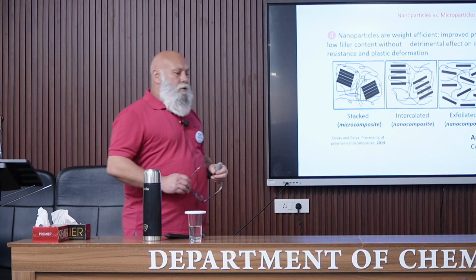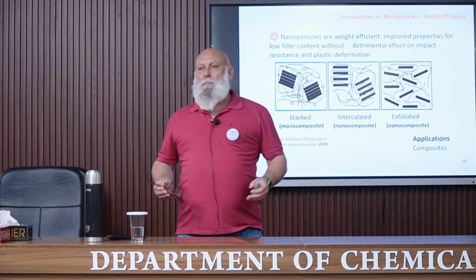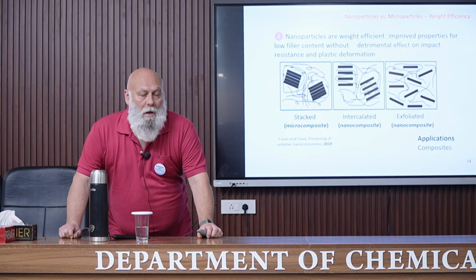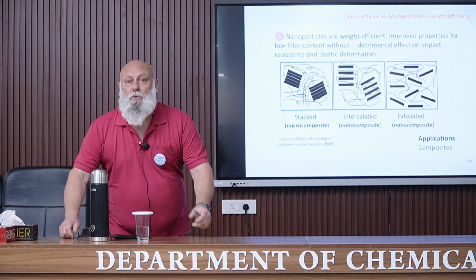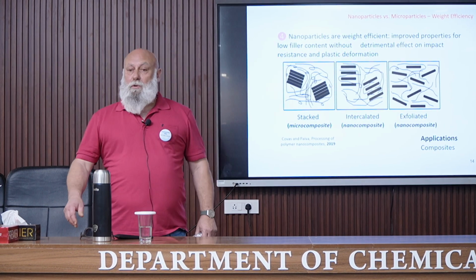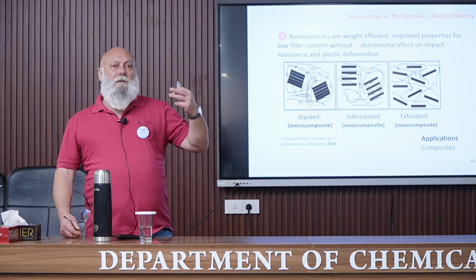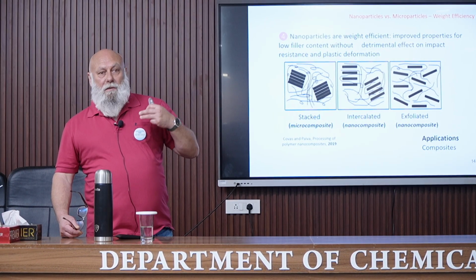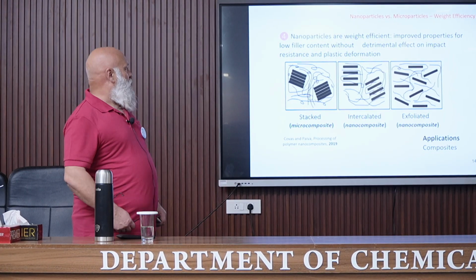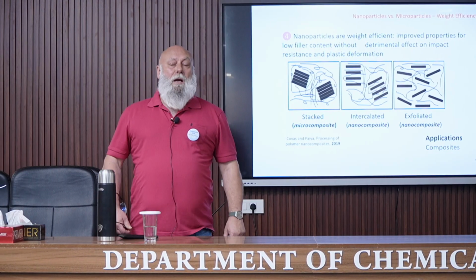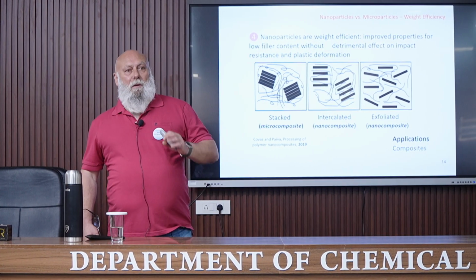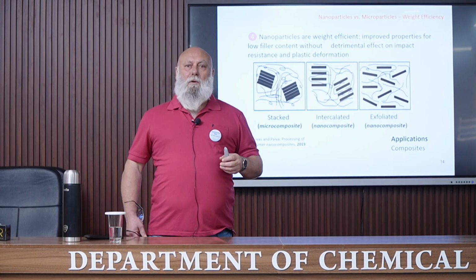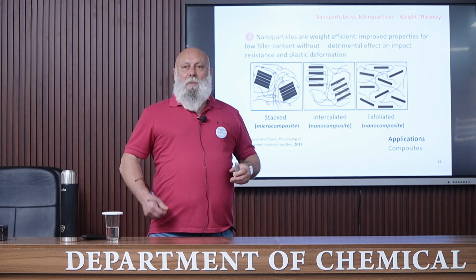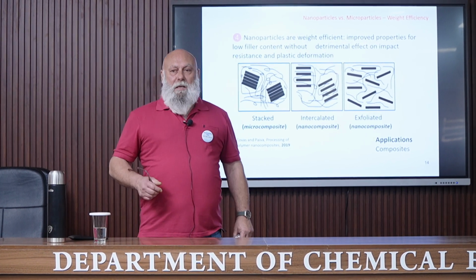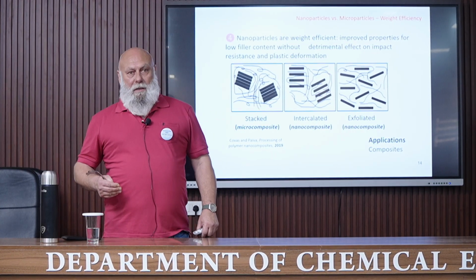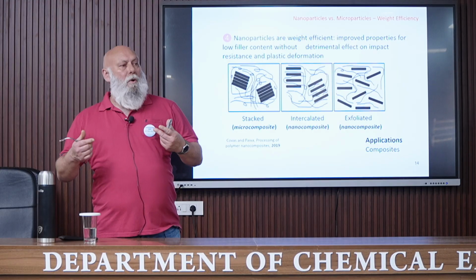What is the meaning of this? In fact, to have a reinforcing effect in composites or biocomposites, it's generally necessary to use around 30% fibers to significantly improve the modulus of the material. Of course, when increasing the stiffness of the material, the ductility decreases, meaning that the elongation at break decreases. The material becomes more brittle. When using nanoparticles, usually only a few percent of nanoparticles is necessary to significantly improve the stiffness of the material. So it's typically less than 5%, meaning that there is a big amount of matrix that provides the ductility to the material, meaning that the elongation at break remains quite high.